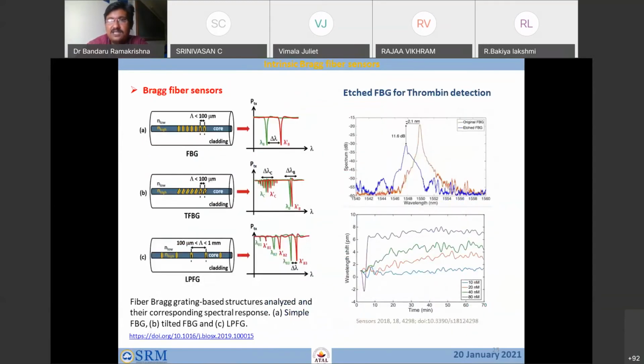After that, some other fiber Bragg grating techniques are also used. What does it mean here? The fiber Bragg gratings reject a particular wavelength, and this rejection of wavelength is sensitive to environmental changes, which means the rejected wavelength shifts here and there with changes in the refractive index around the medium. So any molecule that comes and binds here changes the refractive index, and the reflected wavelength will shift. Identifying this wavelength shift as a graph, you can see that different biomolecular sensing has also happened here.